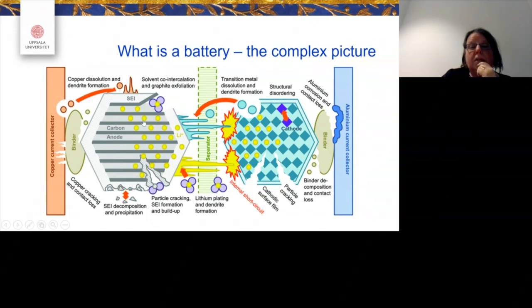You have cracking of particles while this battery is cycling back and forth, with the lithium ions intercalating into the atomic structures on the negative side or the positive side. And you have a buildup of interface layers between the electrolyte and the electrode, and you can have corrosion reactions. You have particles that you have to optimize in size, and they are mixed in a slurry with conducting extra small particles, often of carbon, and they have a rubber type of polymer binder to keep this electrode together, and all this can react in different ways.